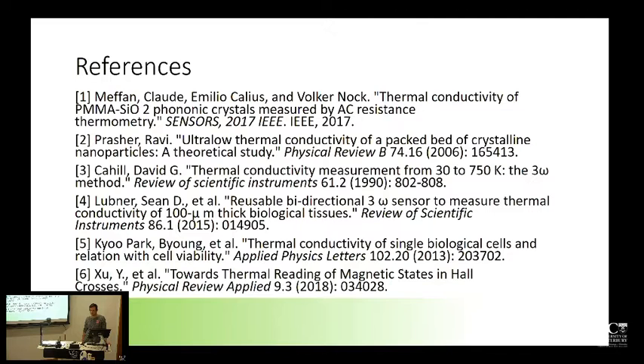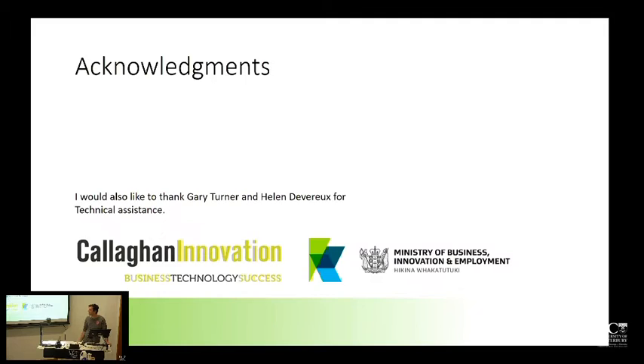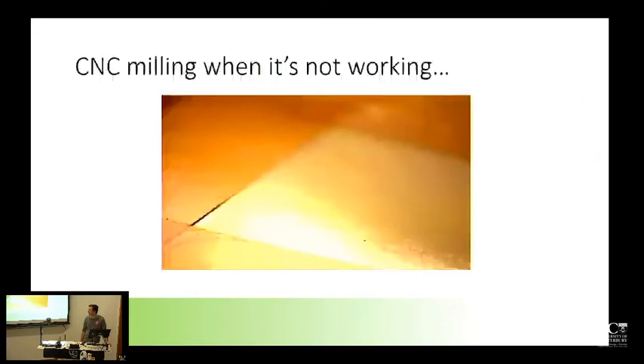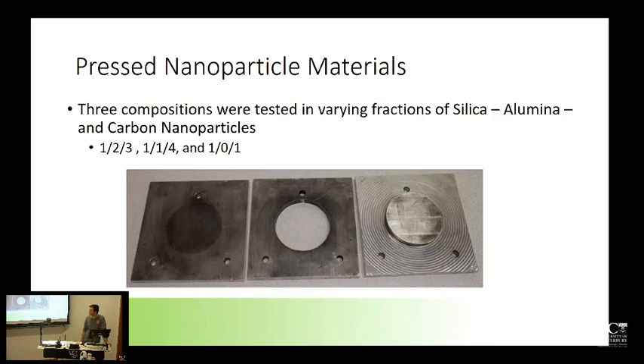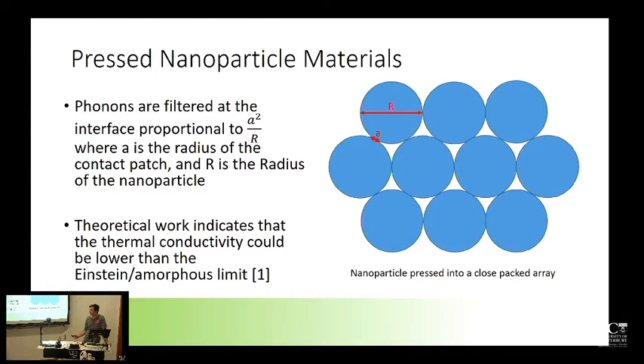What's your theory why the vacuum produces a lower thermal resistance? I don't think you mentioned it, but I know we've discussed it. Yeah. So there's two competing theories here. One of which is that the whole premise of the packed nanoparticle beds depends on this radius of constriction being small relative to the radius of the nanoparticles. However, if there is any moisture which is absorbing onto the surface of them, you're essentially going to get a moisture wick which runs through there and increases that relative radius of constriction substantially.